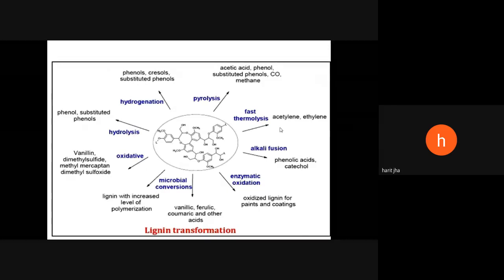Now, if you transform lignin or break or modify it using chemical or biological processes, it can be converted, for example by pyrolysis, into acetic acid, phenol, substituted phenol, carbon monoxide, etc. By fast thermolysis, it can be converted into acetylene and ethylene. By alkali fusion, it can be converted into phenolic acids and catechol. By enzymatic oxidation, oxidized lignin for paints and coatings. Using microbial conversion processes, it can be converted into vanillic acid, ferulic acid, coumaric acid, and other acids. Hydrogenation, hydrolysis, and oxidative processes can also be used for formation of phenol, cresols, vanillin, dimethyl sulfide, dimethyl sulfoxide, etc. So many different types of products can be obtained by lignin transformation.